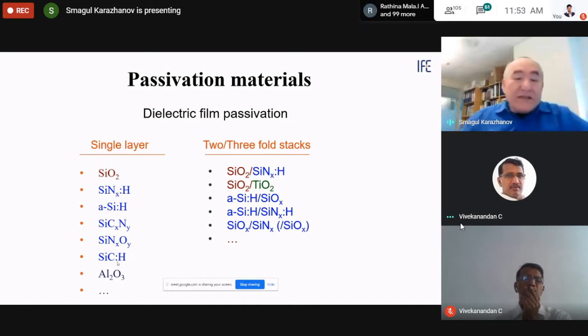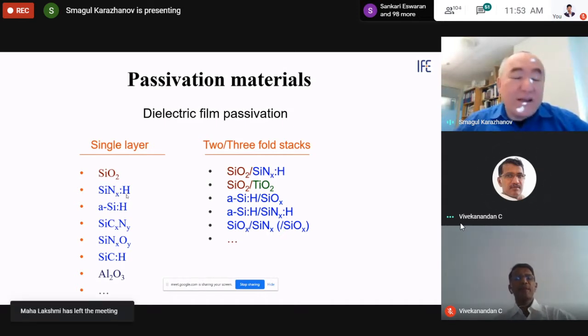So now we see it is good to use silicon oxide, but there are challenges. Another candidate is silicon nitride, which is hydrogenated. When it's hydrogenated, its band gap is above 3.3 electron volt, and it passivates the silicon surface very well. However, the passivation is very good provided the silicon surface possesses N-type electrical conductivity. It should be very highly doped, and it should be N-type. N-type conductivity can be done by phosphorus, and doping with phosphorus is not an easy task.